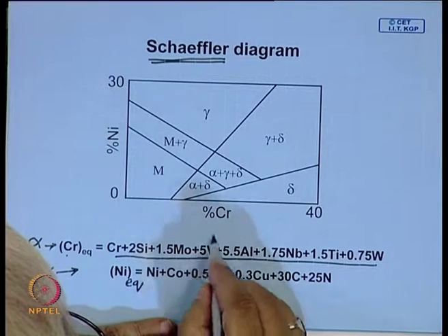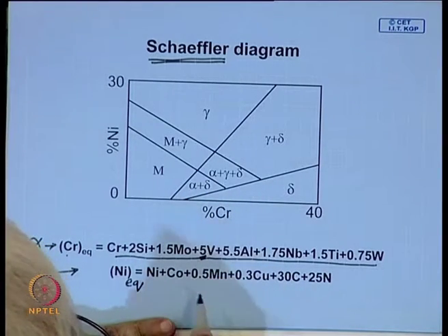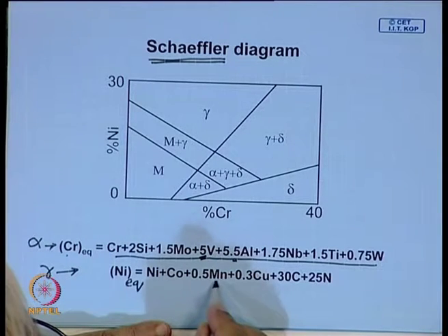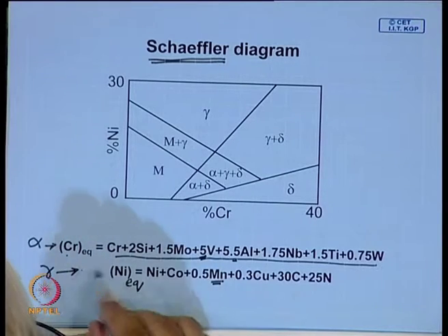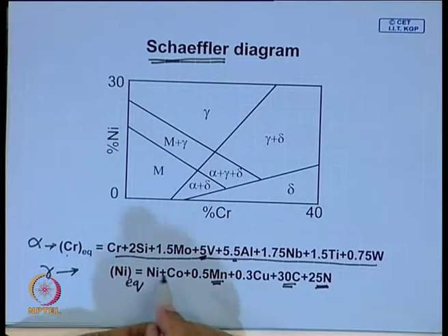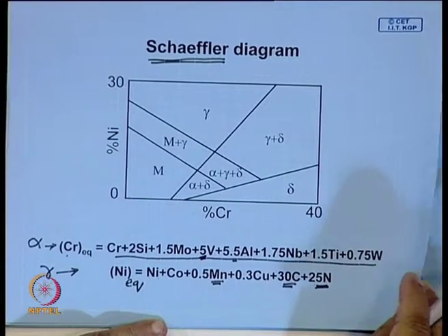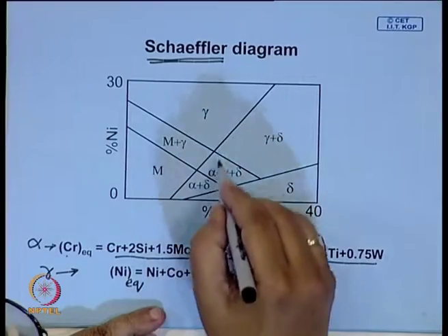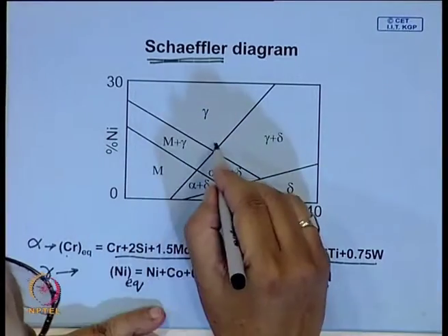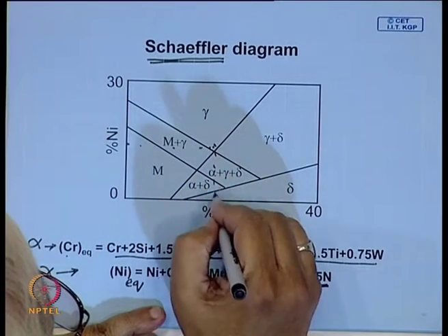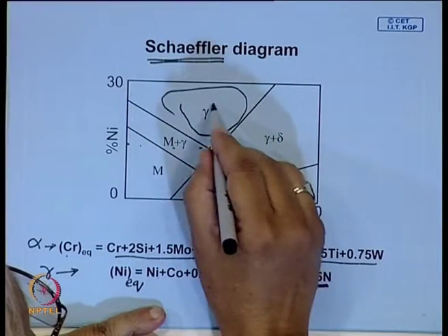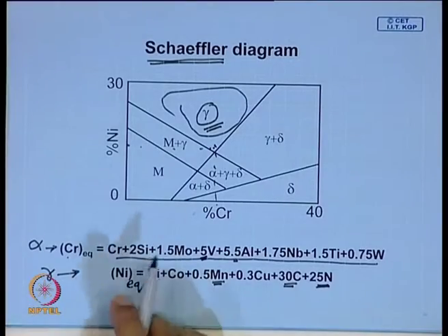So, some of the elements are known as very strong ferrite formers, they raise the temperature in which ferrite is stable. Look at the vanadium, aluminum, they are very strong ferrite formers. Similarly, there are certain other alloy elements like manganese which stabilize austenite. Carbon is a strong austenite stabilizer, so also nitrogen. So, for austenitic grade you try to have a high amount of nickel and some of these austenite stabilizers. And it is possible if you have chromium equivalent around here and nickel equivalent here. So, from here onwards, in all this region you will have austenite stable at room temperature.